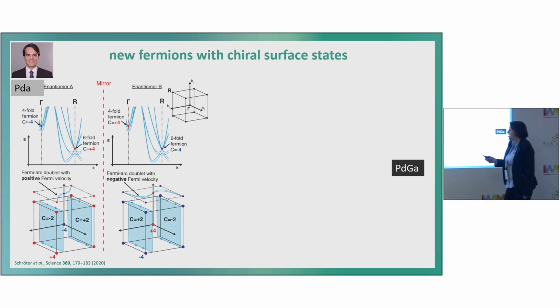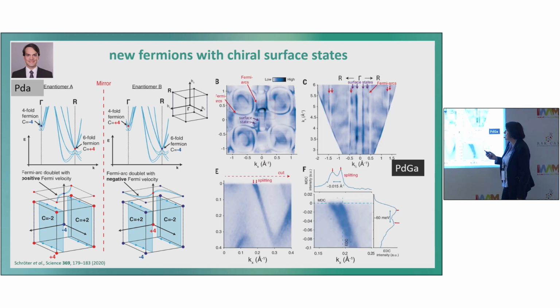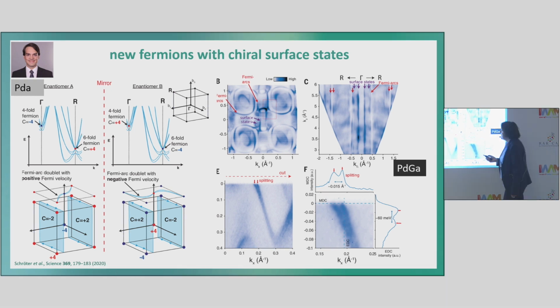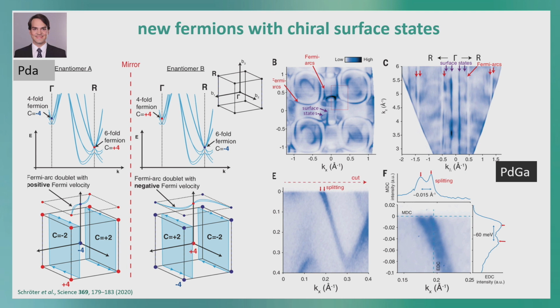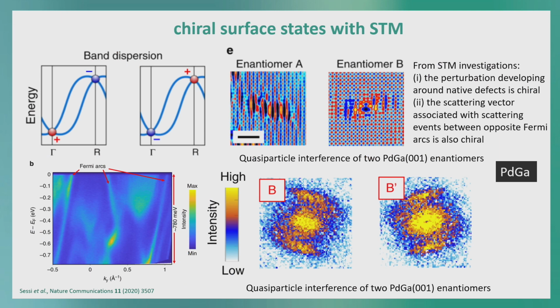We prove this in photoemission, and indeed we can prove it for the surface state. So we look very carefully at the surface state. One surface state has a negative slope. I don't show the other one here, it has a positive slope from the other Chern number, which already gives you the sign. And since we see the splitting here, we even could show that our Chern number is +4 and -4 in this material. You see the same also in STM.